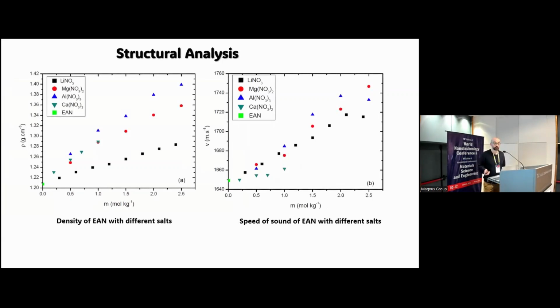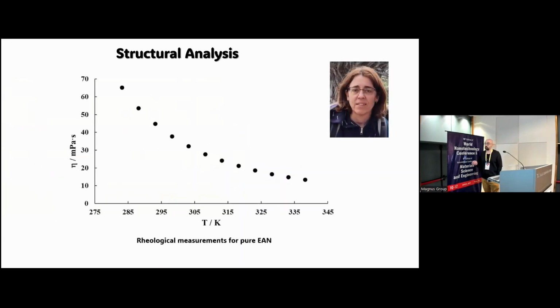Structural analysis has revealed that the density and the speed of sound increase monotonically when the salt concentration is increased. We have also, Professor Maria Villanueva has measured and analyzed the rheological measurements of this ionic liquid. In this case, it is the pure one. And you can see how the viscosity decreases with the temperature, as expected.